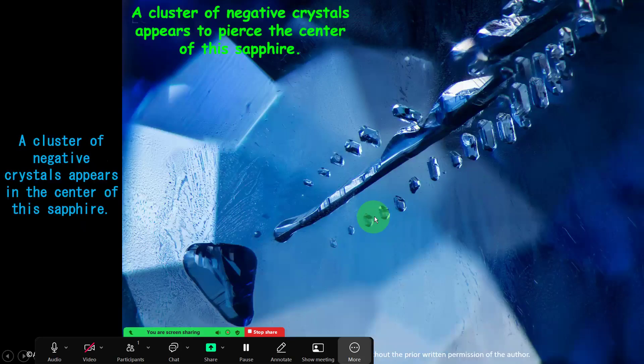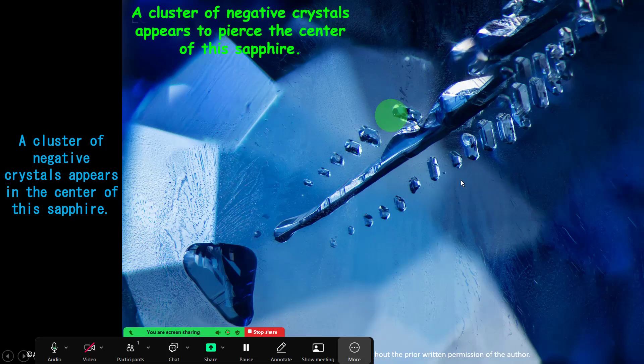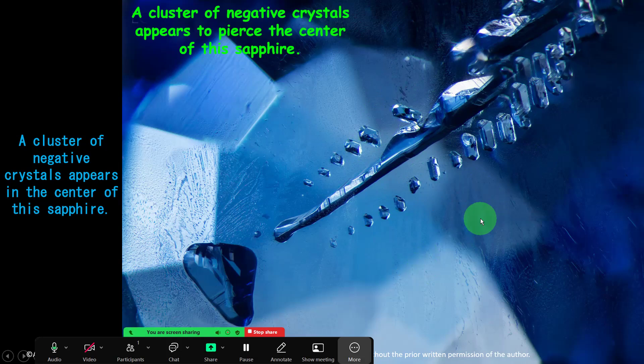Look at these — these are large negative crystals, all called negative crystals. There is a cluster of negative crystals in the center of this sapphire. Look at the fingerprints here — when we see this, we can identify the gem is natural, not heated. So when we heat the gem, these inclusions will change and be destroyed. The inner inclusions will be destroyed and give us some evidence to identify it as a heated sapphire. So we are discussing only the natural sapphires here.